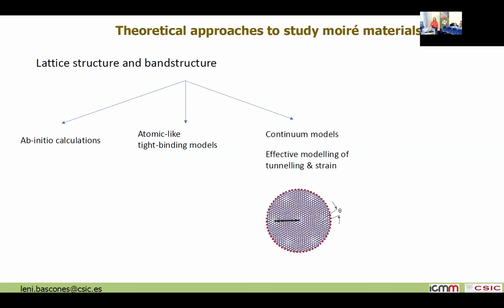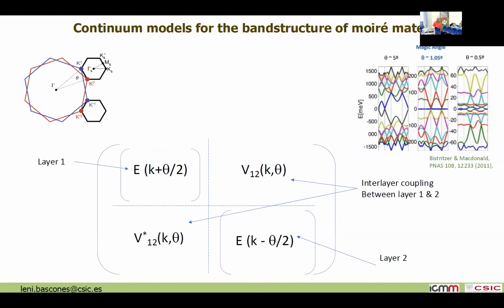Something that people are doing a lot in these moiré heterostructures is using continuum models. With continuum models you lose a bit of information on the atomic distance. So normally you play with the system either in k-space or in real space, assuming it's continuum in the sense that you don't care about this discretization between the sublattices. You have the graphene sublattices, but you lose a bit of the discretization. Let me give you an idea of how this is done. In particular, this famous picture of the magic angle was done using a continuum model, when it was studied.